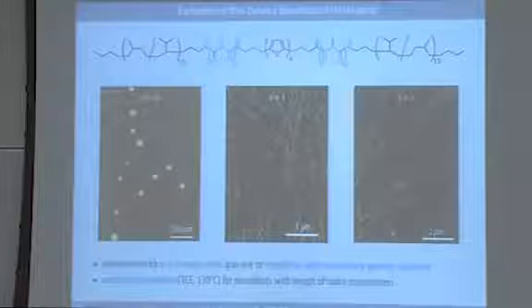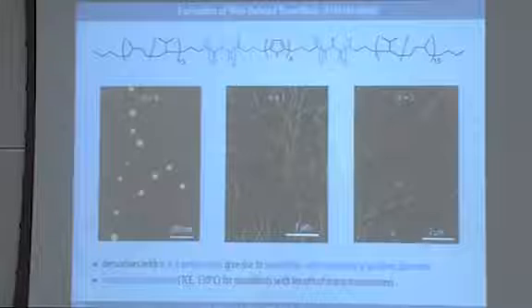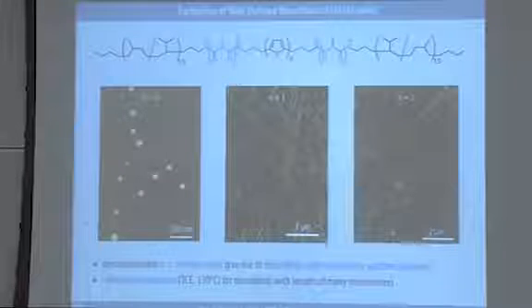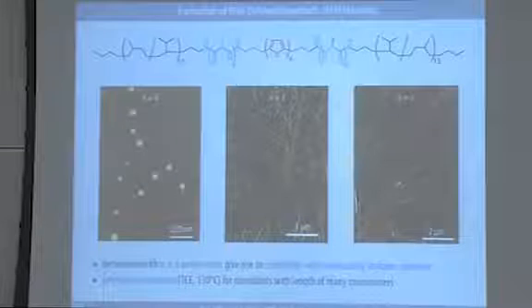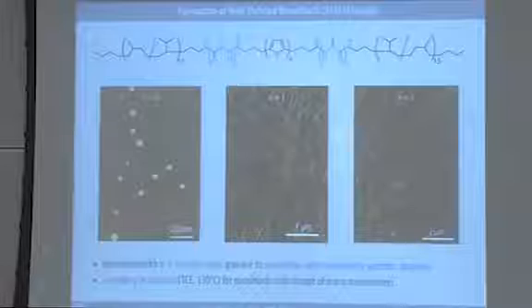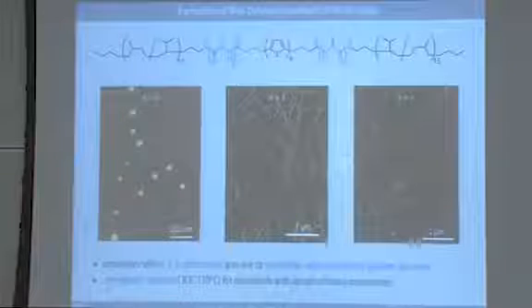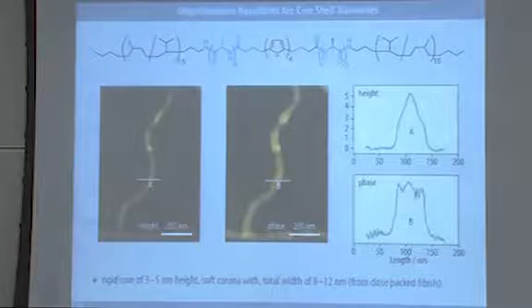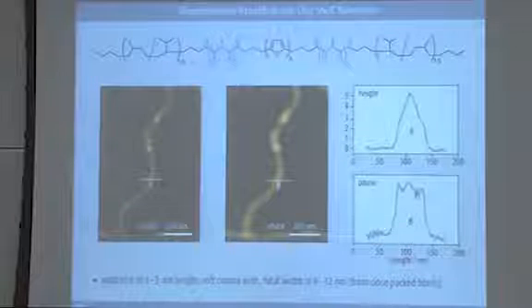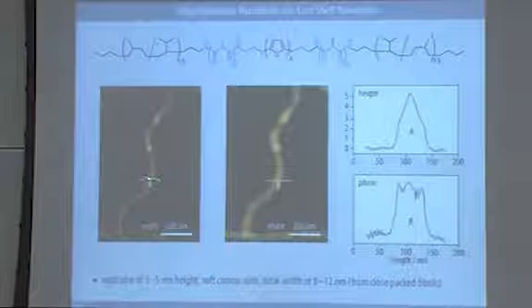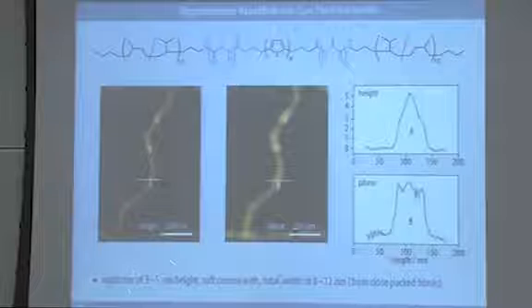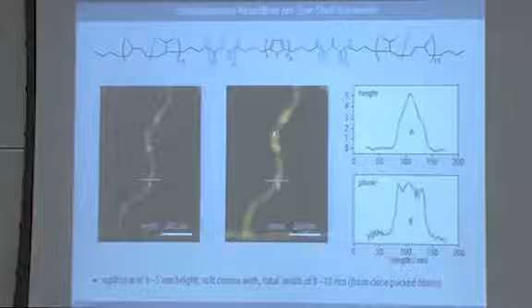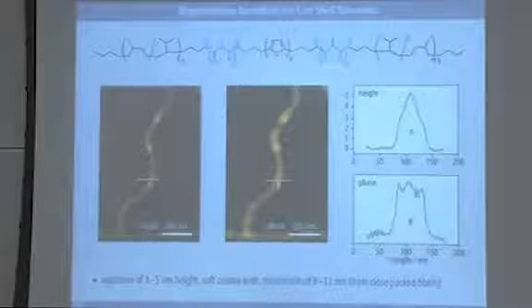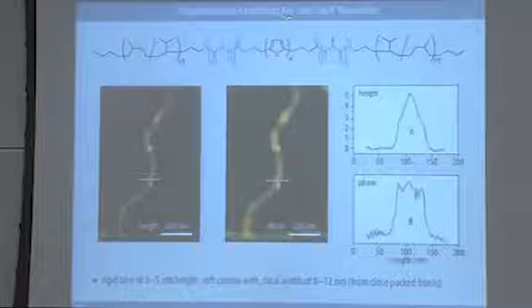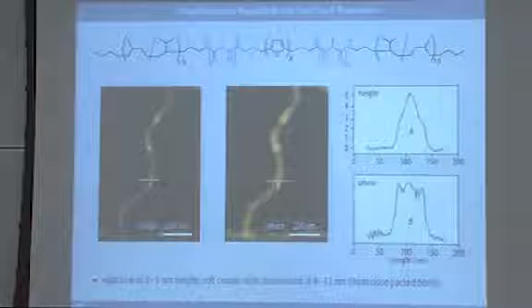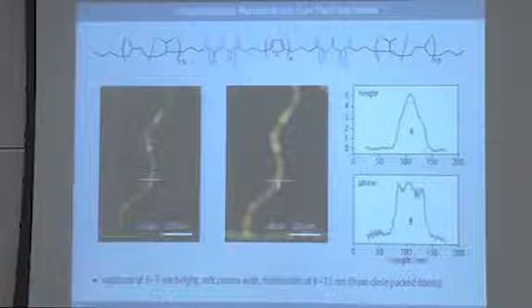So what happens at higher concentrations is you still do not form bundles. You may see that fibrils align close to one another, by a weak penetration of their polymer shells. However, mainly you obtain the same kind of fibrils that are just crossing each other and form a random spaghetti-like network. If you take a closer look at the AFM images and vary a little bit the tapping conditions, you see that actually the fibrils have a rigid core with a height on the order of 3 to 5 nanometers that you can also distinguish very nicely in the phase images. And these 3 to 5 nanometers correspond very well to the oligopeptide, oligothiophene, oligopeptide part of the molecule, whereas the soft material seems to be placed along the flanks of the nanofibrils.